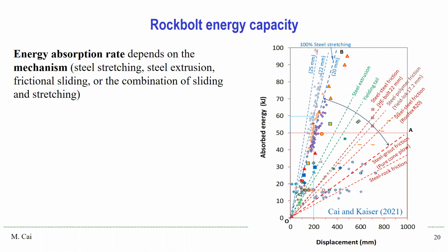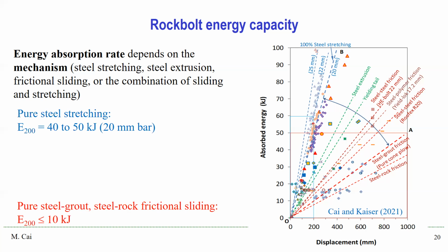We realized the energy absorption rate depends on the mechanism of the yielding bolt, whether it's steel stretching, steel extrusion, frictional sliding, or the combination of sliding and stretching. When you have pure steel-steel or steel-rock frictional sliding, the energy amount at 200 millimeter displacement is less than 10 kilojoules. For pure steel stretching, E200 could be in the range of 40 to 50 kilojoules.